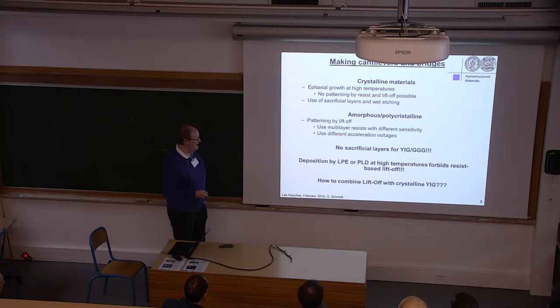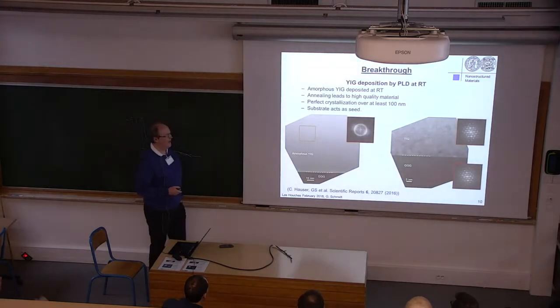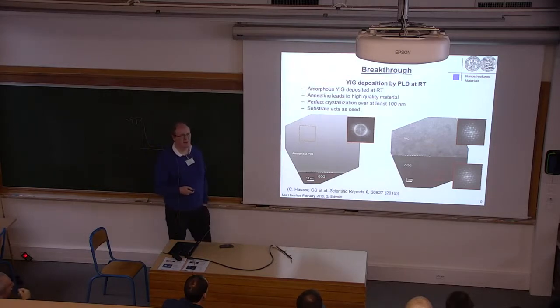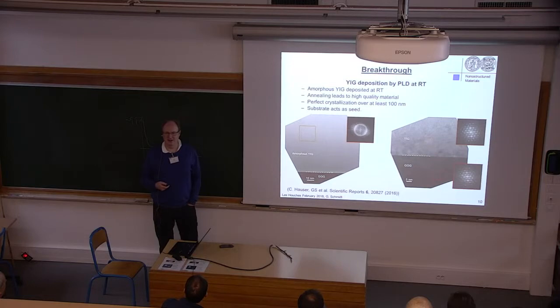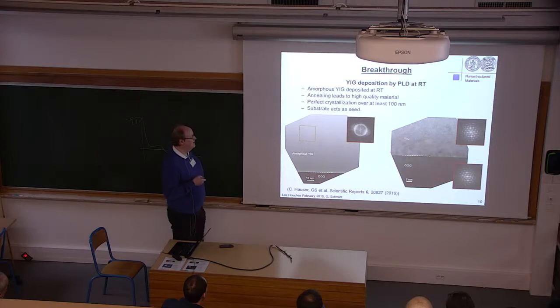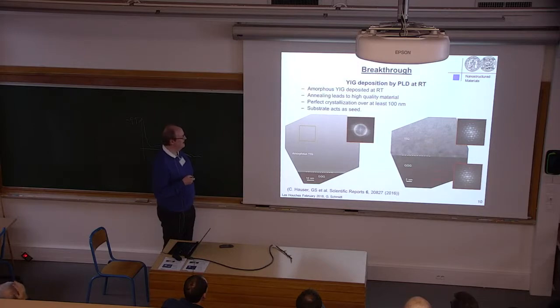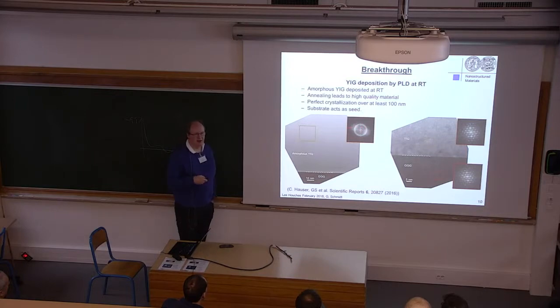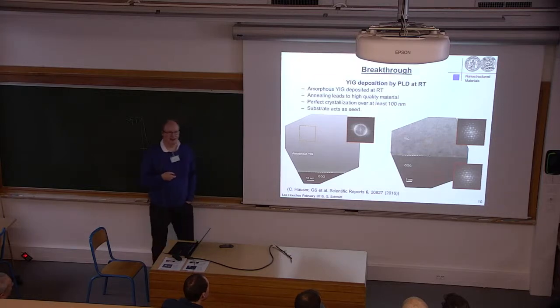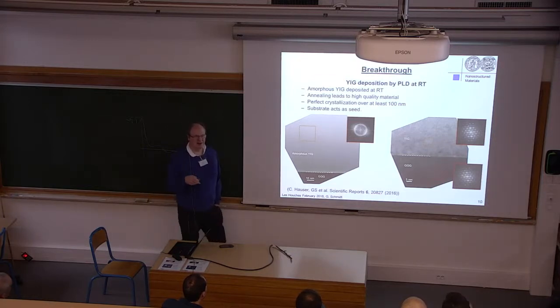So how can you combine lift-off with crystalline YIG? And there, already some time ago, we had a kind of breakthrough, although we didn't understand how far this would actually go, because we did some YIG deposition by pulsed laser deposition at room temperature. And this way you deposit amorphous YIG. You can see here transmission electron microscopy images, and the Fourier transform shows you that there's some order, but it's not a crystalline order. However, if you anneal it, it looks like this. We were not able to find any defects, not even at the interface to the substrate.